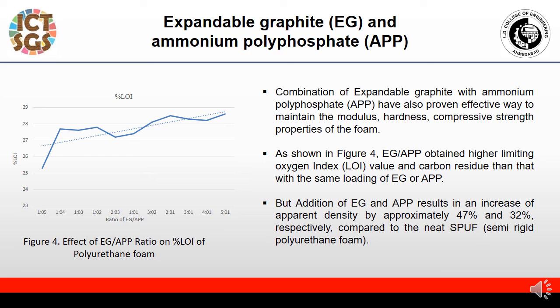The fourth flame retardant is the expandable graphite and ammonium polyphosphate combination. Here the combination of expandable graphite and ammonium polyphosphate has proven effective in maintaining the modulus, hardness and compressive strength properties of the foam. Here in figure 4, it shows the effect of the expandable graphite and APP ratio on the percentage limiting oxygen index of the polyurethane foam, which shows that as the percentage of the expandable graphite increases compared to the APP, the percentage LOI increases.